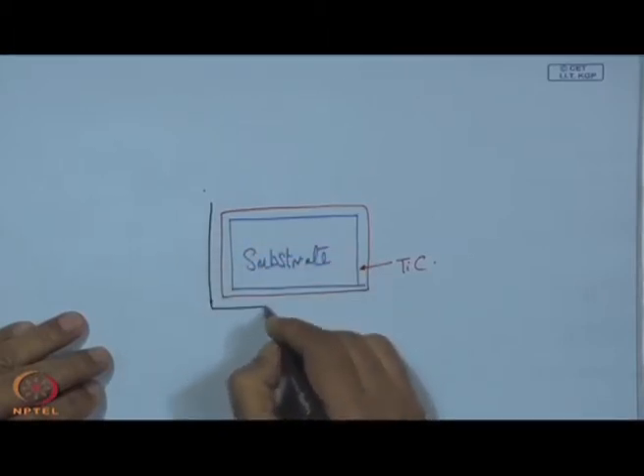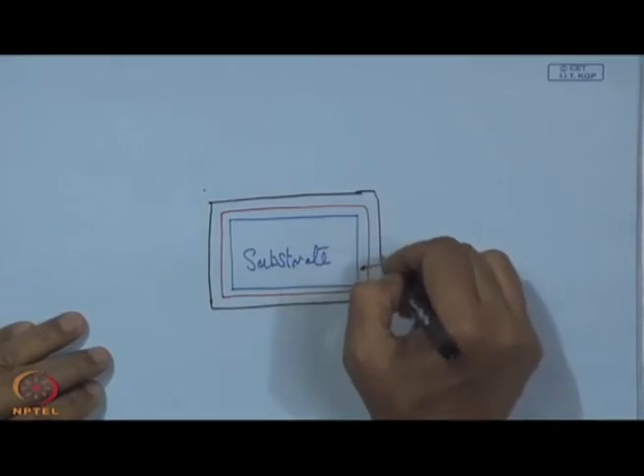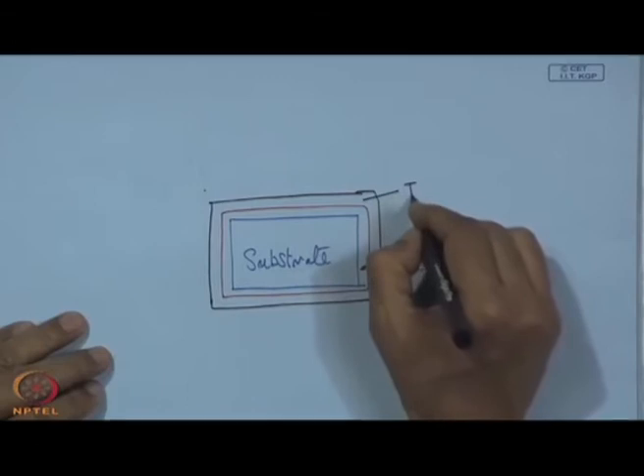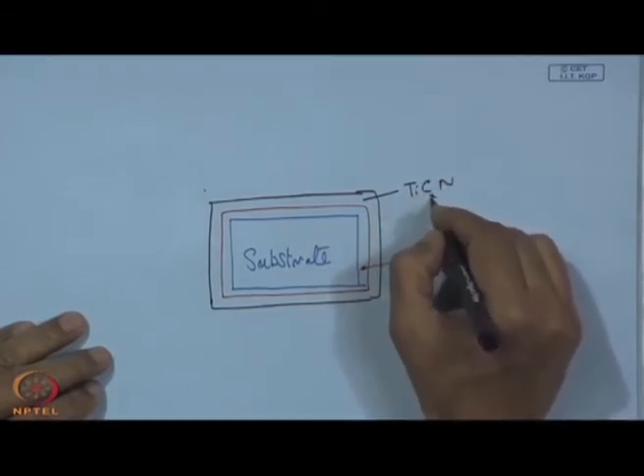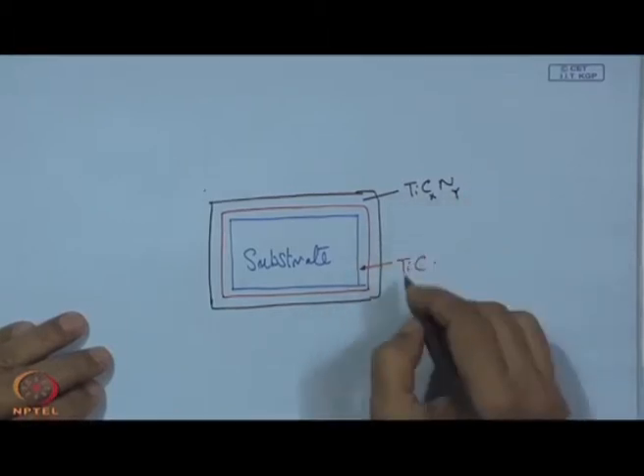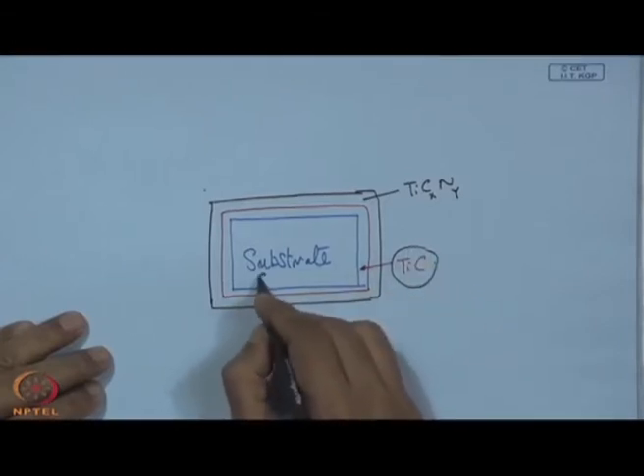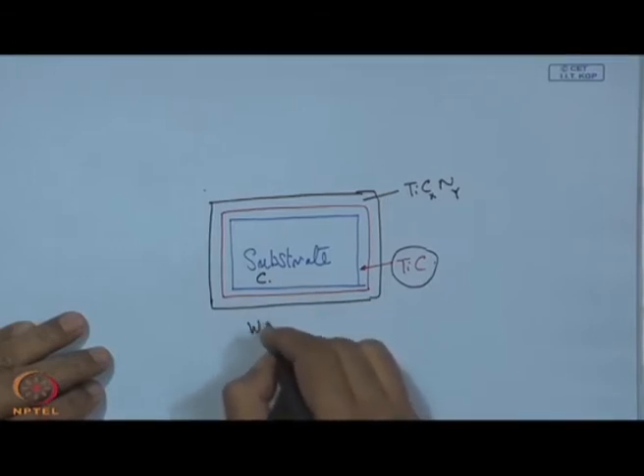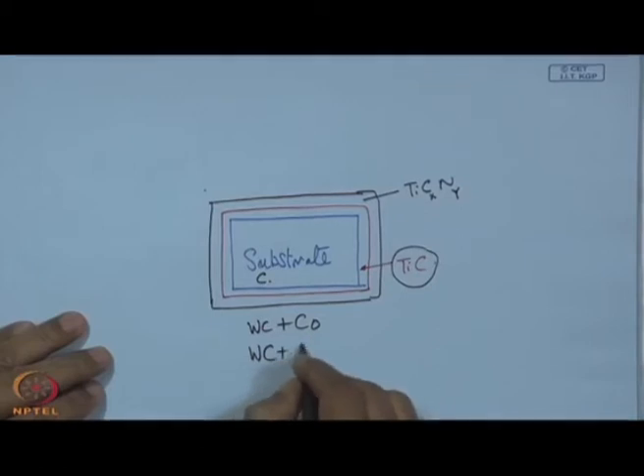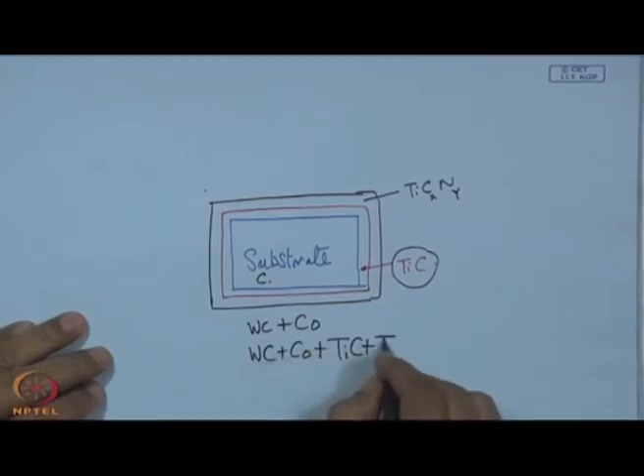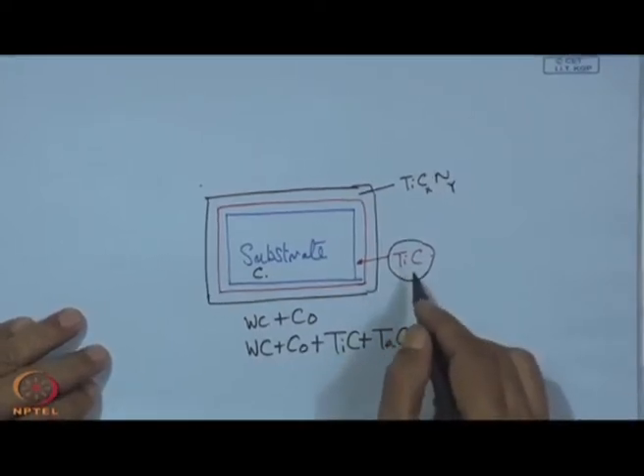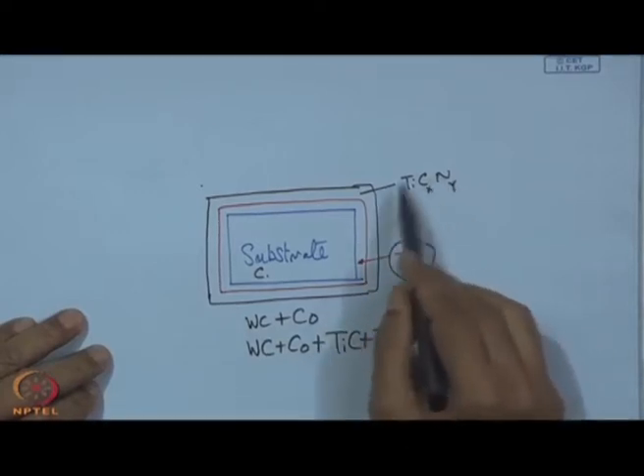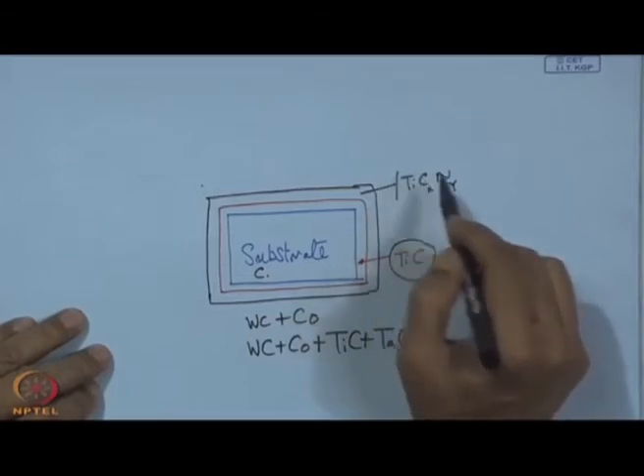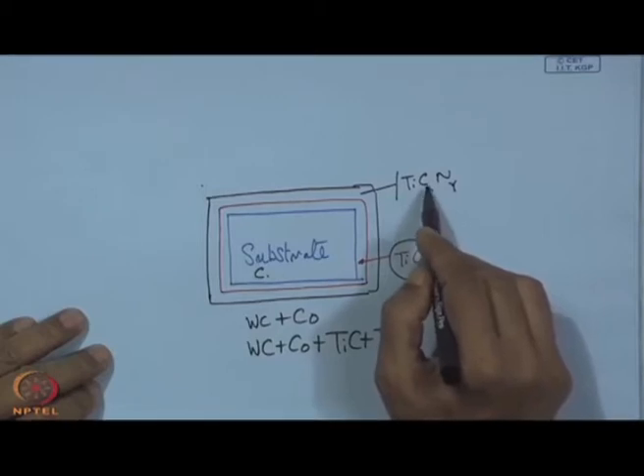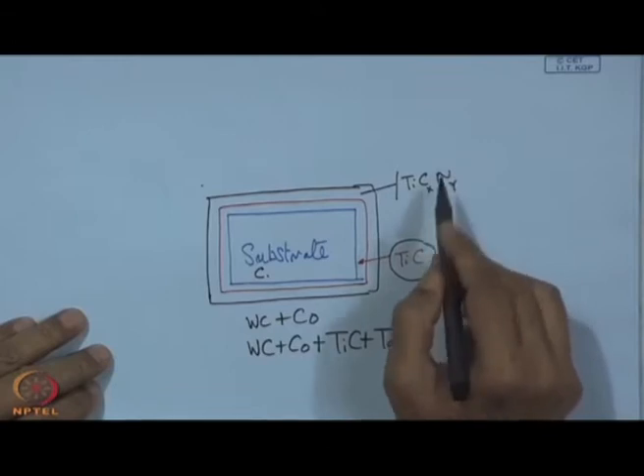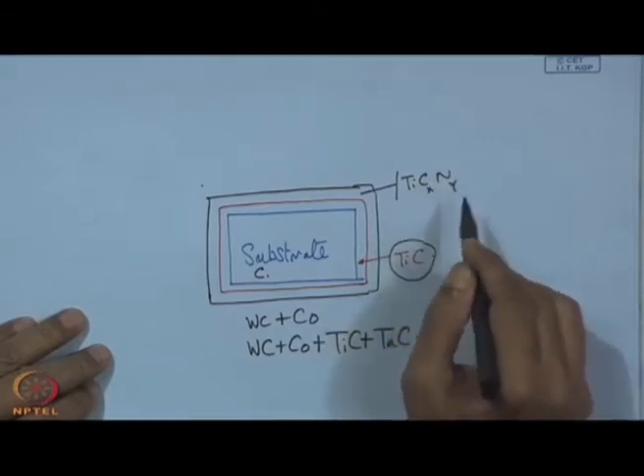But before that, what has to be attained gradually? Here you have a transition layer, which is in fact TiCxNy, with values of x and y. This TiC has very good compatibility with the cemented carbide substrate, which is WC plus TiC plus TaC. This is a formulation, and with that TiC has good compatibility. Then, to bring that compatibility over TiC, one has to go for titanium carbonitride having carbon and nitrogen in that lattice and varying in the values of x and y. So, x plus y is equal to 1.